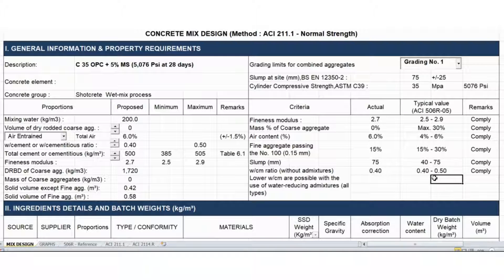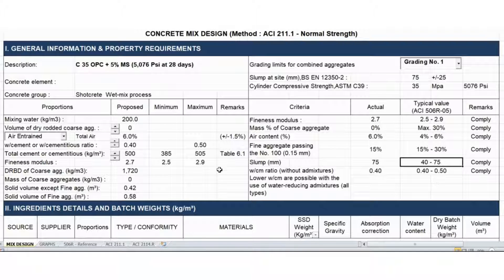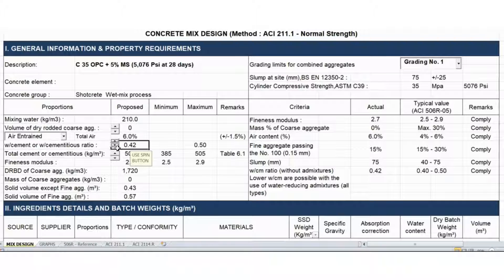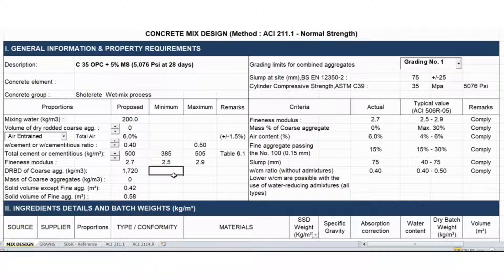Based on my experience, most of the time applicators are asking for a higher slump, but it still depends on the applicator. Moving forward to the left side of the spreadsheet, we can adjust the water-cement ratio to 0.4. I'll be using 500 for the cement content in this example, and water is 200. Whenever I'm using fine aggregates only,